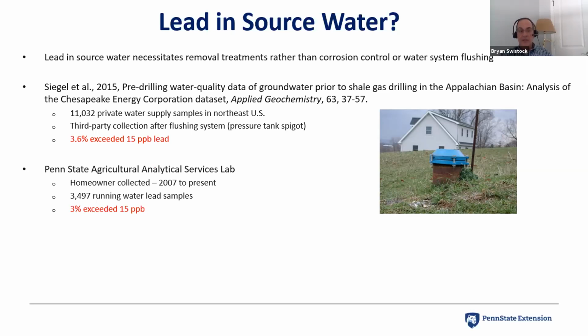Our lab here at Penn State has collected thousands of private water system samples. They are homeowner collected samples, which is an important caveat. And we never know exactly how the homeowner is collecting the sample. We give them instructions, but it doesn't mean they do it correctly. And in that large data set, we find that 3% have lead in running water samples. So these would presumably be samples where the homeowner flushed the water supply out. Now, again, did they do it properly? Did they flush the sample enough? That's always a big question.